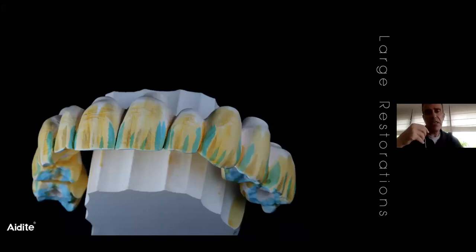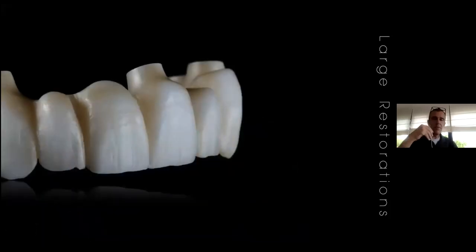A lot of yttrium inside of the restoration is not a good idea because the structure is going to reduce its hardness to less than the initial specifications. You know, with 3D Pro in the occlusal area we have about 600 megapascals, but if we infiltrate with more yttrium, with gray or bluish, it is going to go down. We don't have 600 anymore. Be careful with that. This is a problem for the incisal area when we infiltrate pre-sintering.